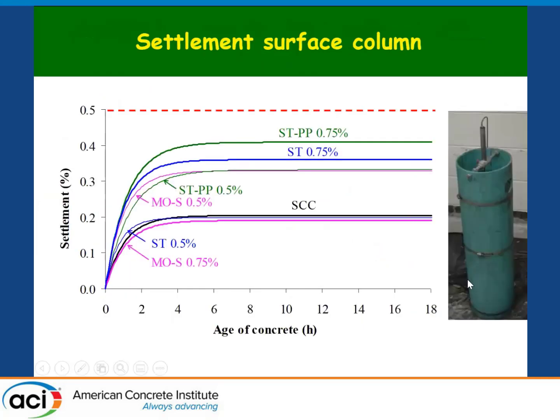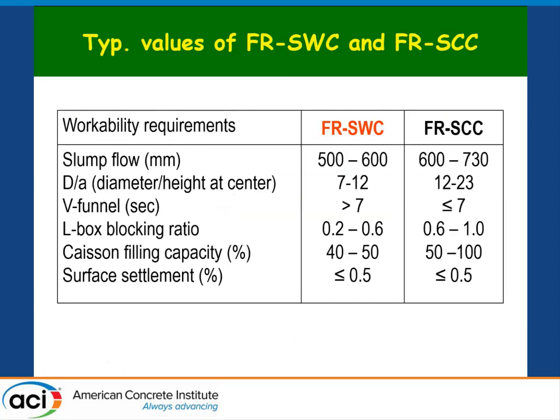And for stability, the test we like to use, in addition to the segregation test, is the surface settlement. The upper level we'd like to shoot for is 0.5% surface settlement. And you can see that the SCCs, the fiber reinforced SCCs, and the fiber reinforced super workable concretes all behaved very well.